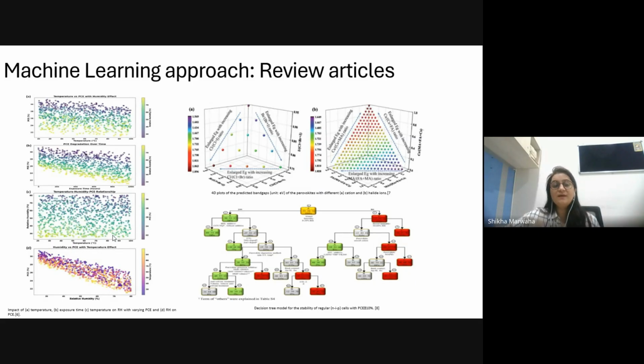The second plot that we can see here is basically a 4D plot. It is used to predict the band gap of a perovskite material with different cations and halide ratios. So here we can see, if I want to see the contribution of one cation at a time corresponding to the other cations, how my band gap is increasing and decreasing.